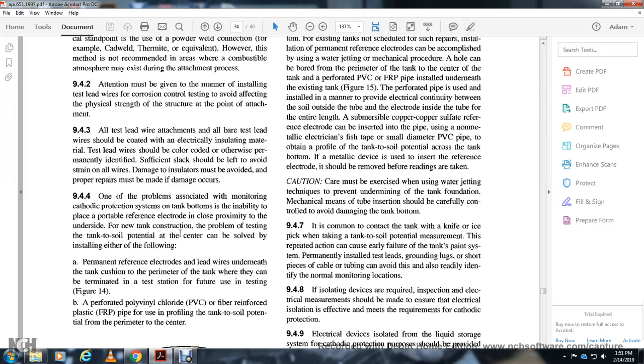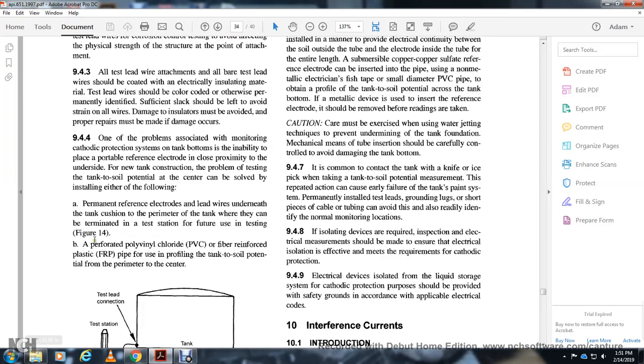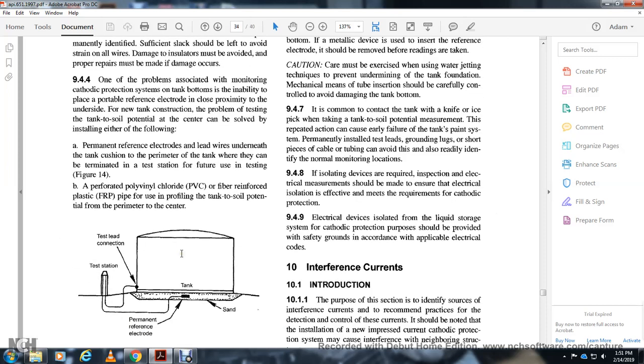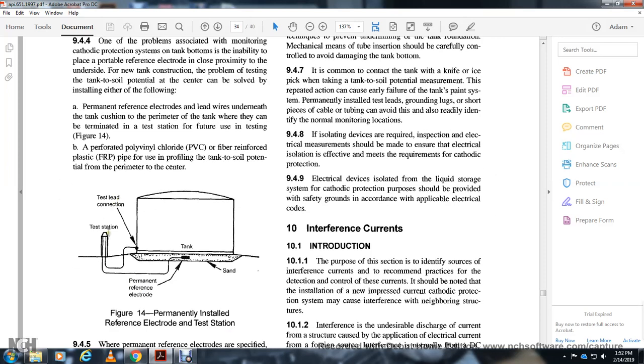One of the problems associated with cathodic protection of tank bottoms is the inability to place the proper portable reference electrode close to the underside of the new tank for testing the tank-to-soil potential at the center. That may be solved by installing either of the following: a permanent reference electrode with lead wire underneath the tank, or perforated polyvinyl chloride or fiberglass reinforced plastic pipe under the tank, which can be connected to the test station for profiling the tank-to-soil potential from the periphery to the center of the tank.